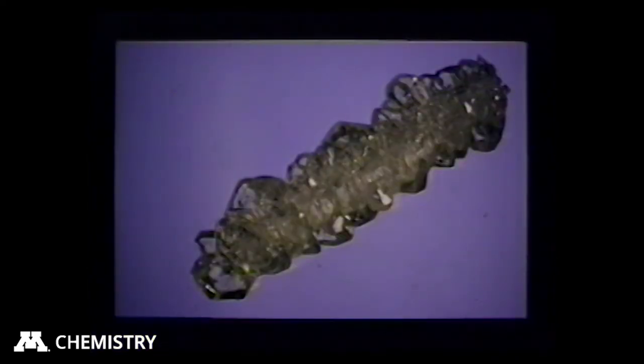Now, if you continue to watch this crystal as it sits in the beaker, what happens is, as the crystal is growing, all of a sudden, you see a diamond-shaped crystal grow at the tip of the needle. And just a few seconds later, down the side of the crystal, it goes bing, bing, bing, bing, bing, and you get diamond-shaped crystals throughout the whole crystal, and it looks like rock candy. And so now that single crystal has transformed through a solution-mediated phase transformation into the stable form.